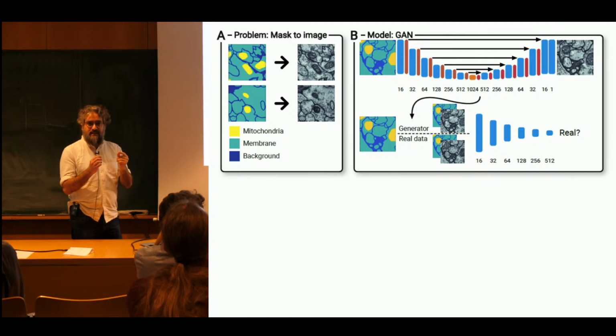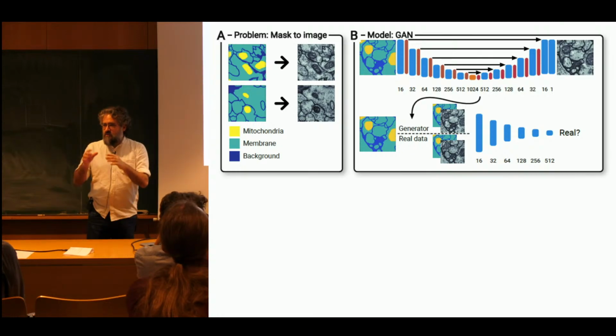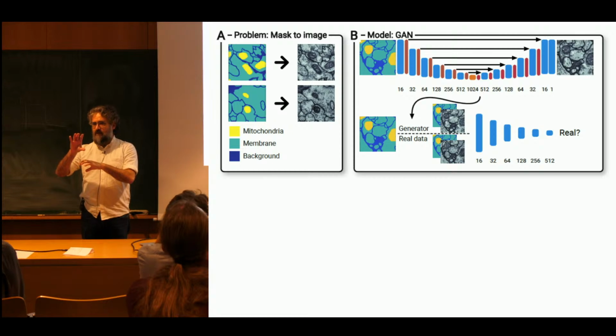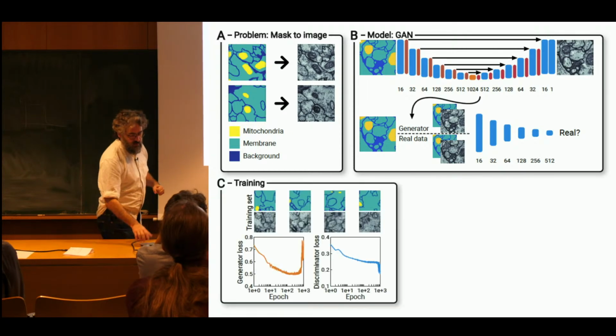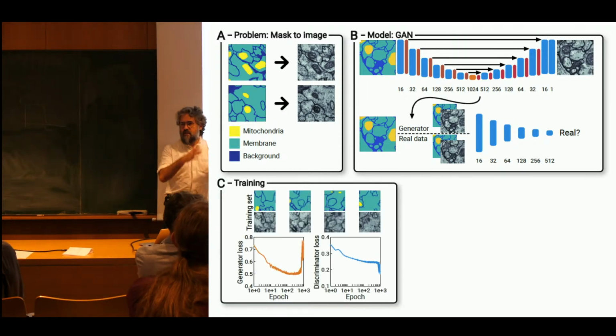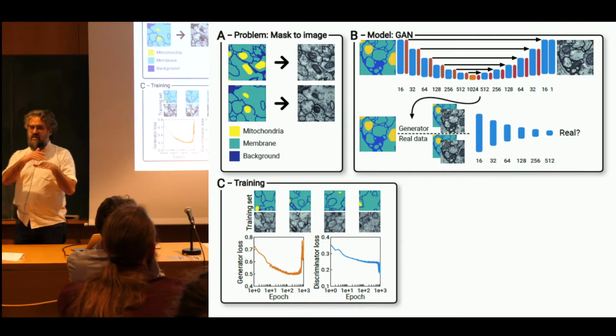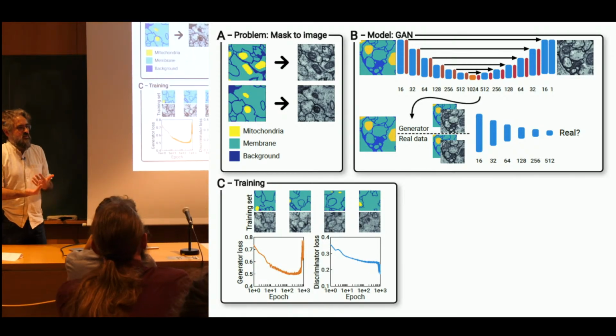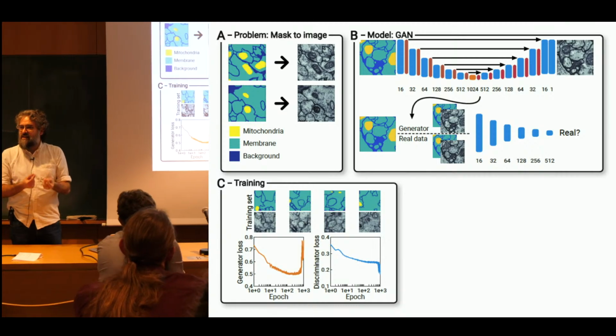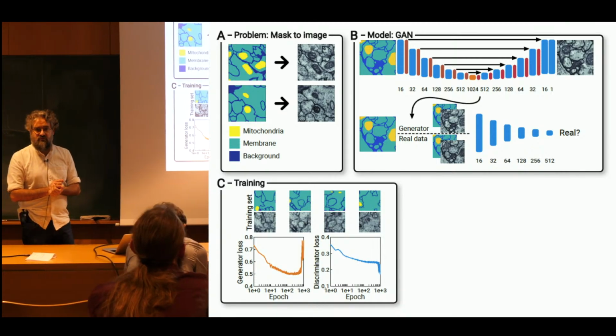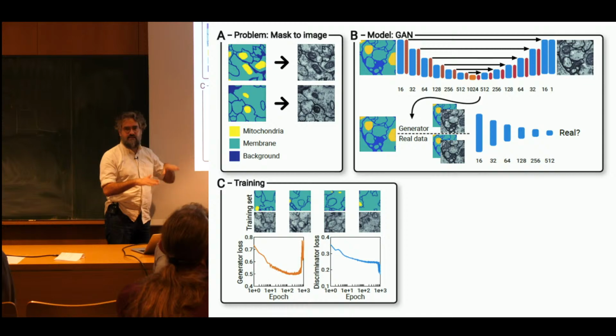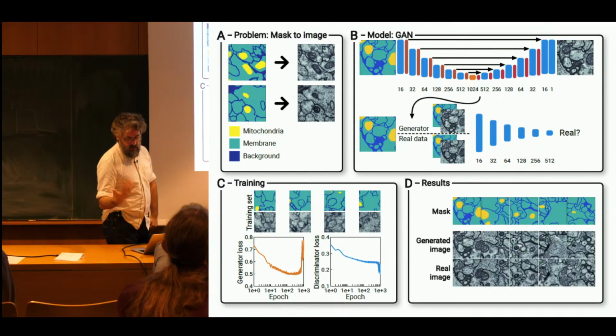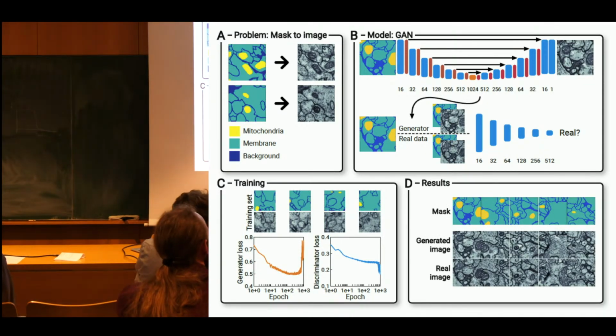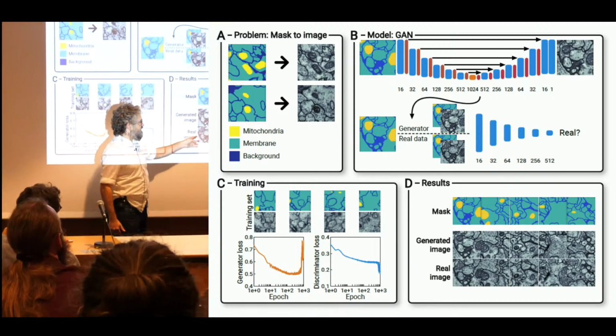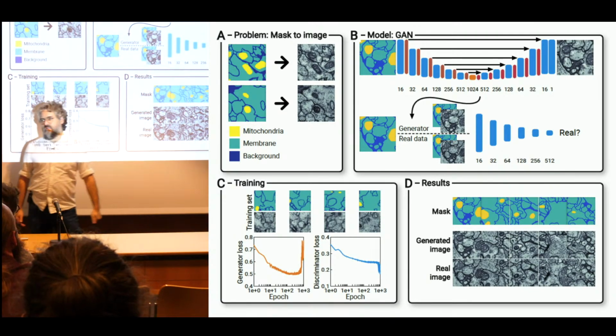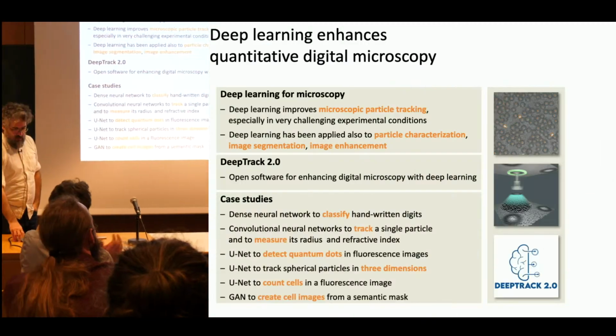The challenge with any generative adversarial approach is that you need to train two neural networks at the same time against each other, which practically means you need to ensure that the losses of both of them decrease at the same rate. If they don't decrease together, if the generator becomes too good or the discriminator becomes too good, there is no real signal anymore in the network to train further. So the real trick here is to balance the losses between the two networks, and it works very well. So the outcome is this one, and you see that the generated image is as plausible as the real image. And with that, I will conclude.